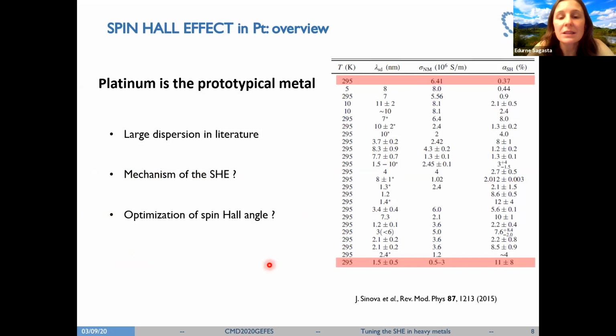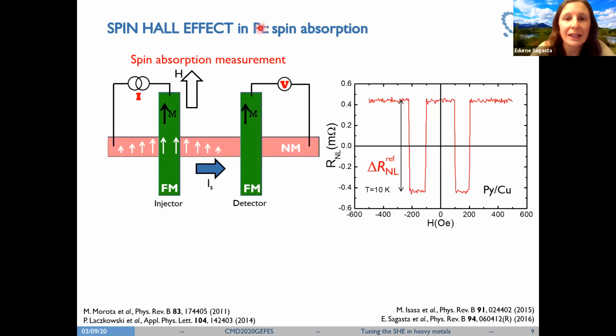So in order to answer these questions, we used the spin absorption technique to study the spin Hall effect. The spin absorption technique is measured by using these lateral spin valves that consist of two ferromagnetic electrodes that are used to inject and detect the pure spin current that will be transported in the non-magnetic metal, which in our case is made of copper. Basically, we inject a current in a closed circuit from the ferromagnet into the non-magnetic metal. And at the right side, we will have a pure spin current generated and injected into the copper that will arrive at the second ferromagnetic electrode, our detector, and we will be able to measure a voltage drop. Dividing by the current, we get the non-local resistance.